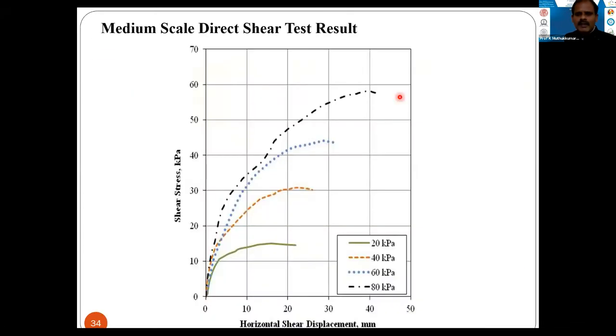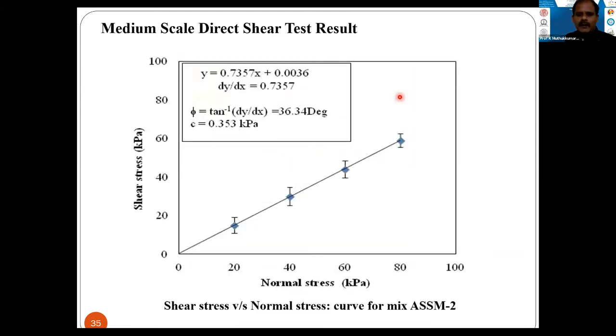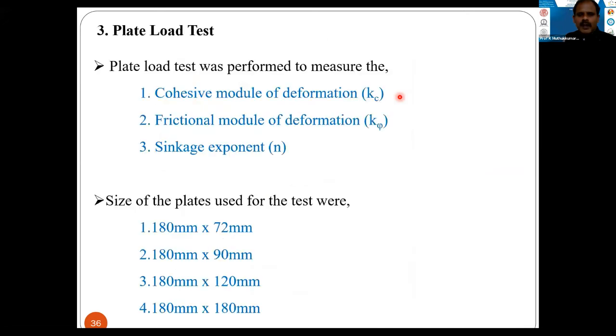So the tests have been extended to all other engineering characteristics, starting from the direct shear test and compaction test, consolidation test, and triaxial test. And basically we want to obtain the potential. The very important aspect is obtaining the sinkage exponent. So basically what will be the sinking capacity of the material. That we have simulated in the laboratory conducting a simple plate load test. The very important aspect is that the rover wheel will be decided based on the sinkage exponent. Basically the sinkage components, especially the cohesive modulus of deformation and the friction modulus of deformation.